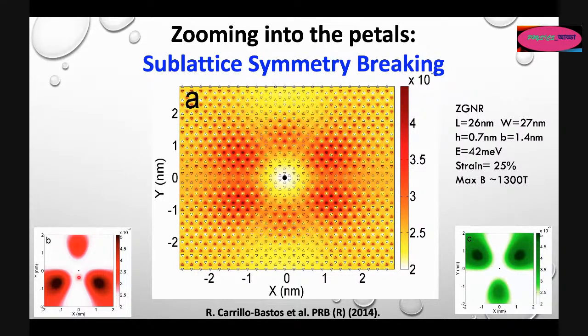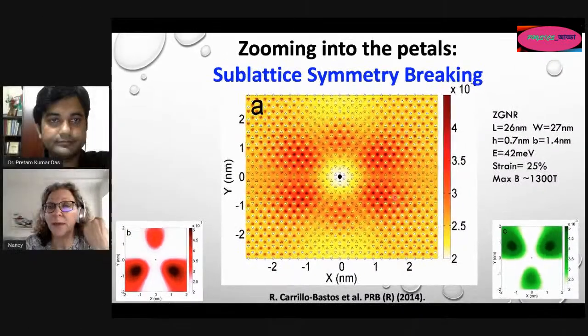So here I plotted the electron occupation, the electron density per sublattice, and you see clearly that one sublattice is occupied while the other is empty, and respectively for the other sublattice here. So the fact that the charge is redistributed in this particular shape tells me that if I am taking an STM image here, I will see only the carbon atoms that host the electrons, and in this case will be the carbon atoms belonging to only one sublattice. While if my STM tip is in a region like this, I will see the other sublattice, but in both cases, I will see only one of them.